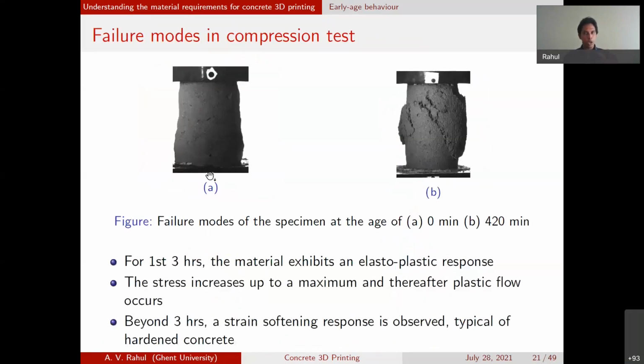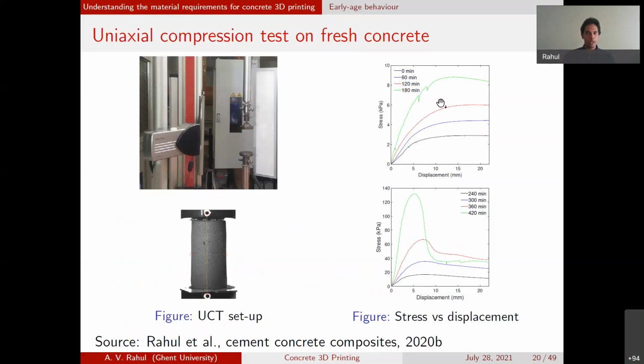It must also be shown how the failure modes differ in the material with respect to age. So if you see the early age material, you see that the material just fails by barreling. So it resists the applied load for some time and then it starts to flow out or barrel, undergoing indefinite plastic deformation, as you see here. And this is also very typical in the material behavior that we characterize. We see an elastic response, and then we see an indefinite plastic deformation occurring in the material.